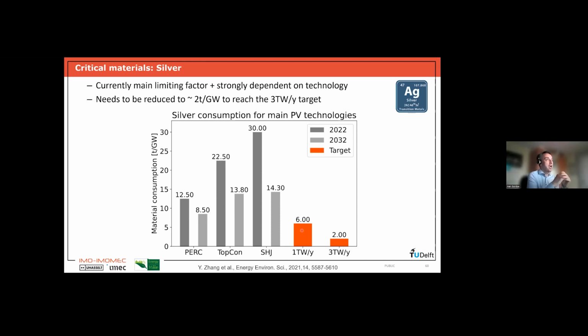So we assume that we have a maximum of, let's say, 20% of the worldwide silver that we can ever use for PV production. Then we can calculate that if we have 1 terawatt per year of production, we have a limit of 6 tons of silver that we can use per gigawatt. If we want to produce 3 terawatt per year, then of course this is lowered by a factor of 3, and it's only 2 tons of silver per gigawatt.